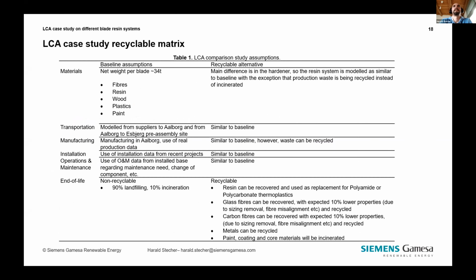So at the end of my presentation, I want to show a study based on LCA presented here that has been introduced. So the idea is to estimate the positive effect of the application of a recyclable matrix. So basic assumption is that a resin is used that offers the same properties, but does not need adjustments in the process and can be recycled under mild conditions. Fiber properties are decreased by 10%, and after the recycling, the matrix can be reused for less demanding applications, e.g. as a replacement for polyamide or polycarbonate.